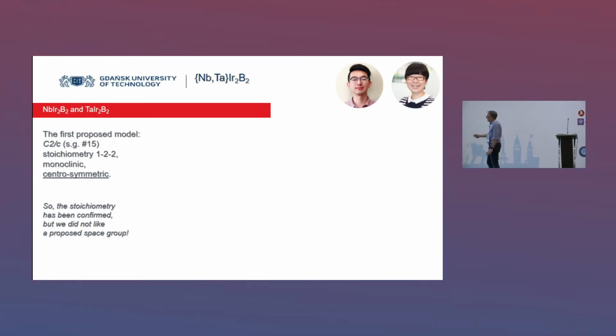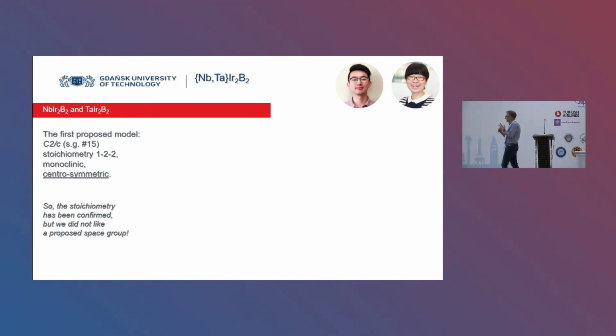They confirmed stoichiometry, 1-2-2 to 2. They confirmed it's monoclinic, but centrosymmetric. And actually, we didn't like it. We didn't like it for 2 reasons. The first reason is that we already observed very high upper critical field. For centrosymmetric, just the typical BCS superconductors, you cannot go above the Pauli limit, which was actually our case. And the second thing is that when you get the crystallographic table, you try the Rietveld analysis of your powder X-ray diffraction, and it didn't work.